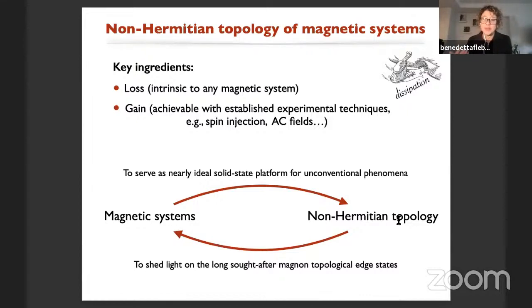Actually, we would like to get rid of these dissipations on many occasions, and we just cannot. On the other side, we also would like to be able to control loss and ultimately the effective lifetime of quasi-particles, and we can do that by controlling the gain. It turns out that we already have very well-established experimental techniques that allow us to control the gain, and I will show an example today. For example, one of them is spin injection, but AC fields, for example, can do the job.